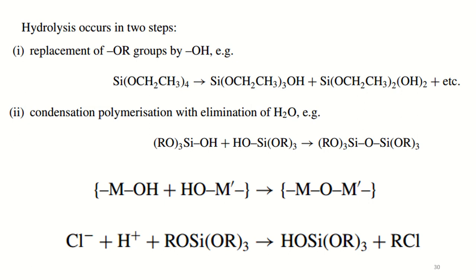As shown in this equation, it is quite essential to achieve M–M' cross condensation instead of separate condensation of each component. Hydrolysis may be base-catalyzed with nucleophilic substitution by OH⁻, or acid-catalyzed with electrophilic attack by H⁺ or hydronium ion. The final stage is to heat or calcine the gel to decompose organic matter and leave an oxide product.